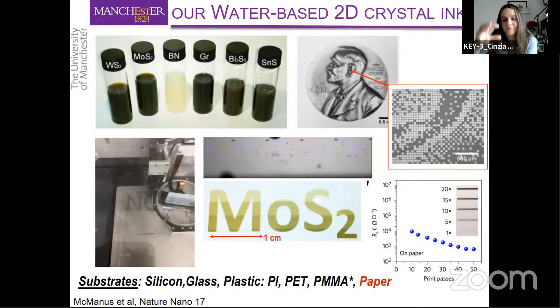And so when we print on paper, the solvent will be absorbed very quickly in the substrate. And so the material will not really have time to diffuse around, produce coffee ring effect, and so on. So by printing on paper, we can deposit a very high amount of material in a very small area, which translates into a very high resolution. For example, here you can see a Nobel Prize medal that has been printed with our graphene ink. And you can see how sharp and nice the features in this medal are.